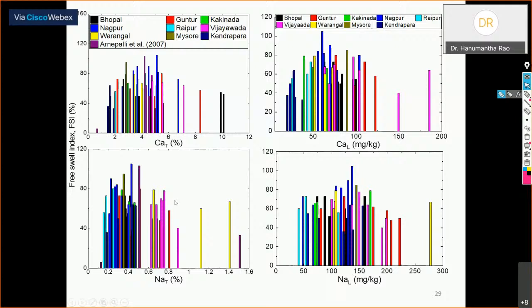Okay, suppose you take any expansive soil and do the XRF analysis for determining the calcium content and the sodium content, and you try to correlate with the free swell index. This is the relationship you will get. Alternatively, if you are unable to conduct the free swell index test, or you want to know based on only the chemical parameters, then this kind of relationship is very handy.